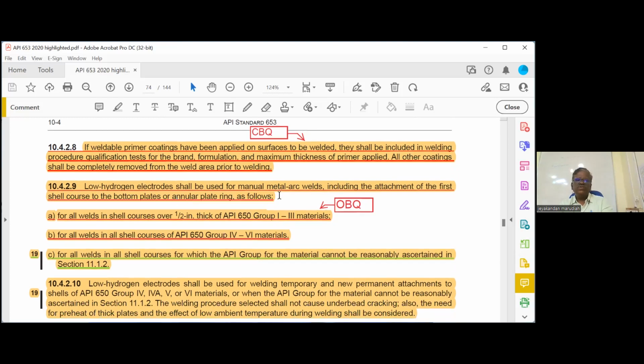Low hydrogen electrodes shall be used for manual metal arc welds, including the attachment of the first shell course to the bottom. For all attachment welds, half an inch thick, group 1, 2, 3 material. For all welds, 650 group 4, 6. This is very important. When low hydrogen electrodes are required, when you want to make any repair on the tank, low hydrogen electrodes only you have to use. Low hydrogen E7018, 7015, 7016. And group 1 to 3, when the thickness is more than half an inch, you have to use low hydrogen. For group 4 to 6, all thicknesses you have to use low hydrogen.